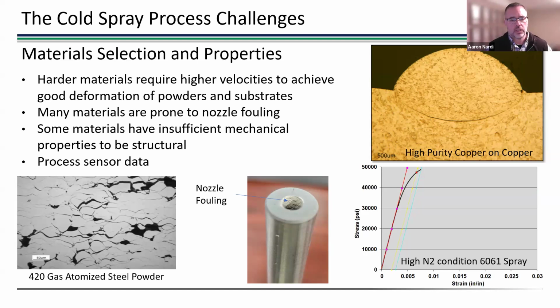So you can also see a couple of other examples. One issue we run into is nozzle fouling. That's that middle image. And that's when we get a material that is really soft or has a lot of fines in it, or there's a lot of reasons for nozzle fouling, but that's another sort of pervasive issue that most everybody runs into at one time or another with cold spray. And then you've got your basic structural properties. How much ductility do you have in the material that you're depositing?